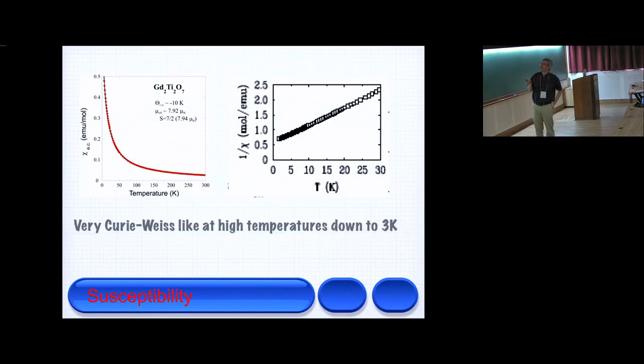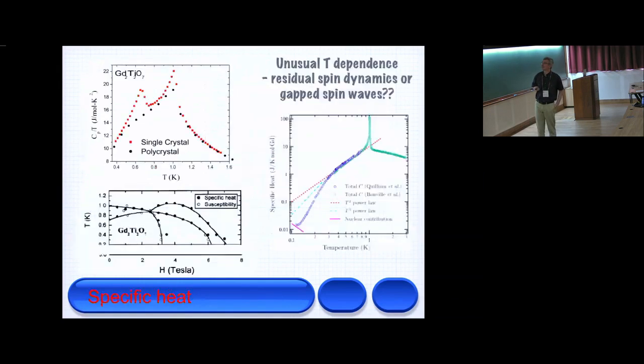And so we always will show, in gadolinium titanate here, and this is stannate, they're both roughly 10. So all we've done is change the B site from one non-magnetic to another. The lattice changes by 3%. The A is a cubic system, so the A lattice changes by 3%. In gadolinium titanate, we see 2 transitions. So already this Palmer-Chalker model is wrong, if you're just looking at this system, it predicted one transition into a well-defined state. In the stannate, there's one nice transition, which is a good sign.